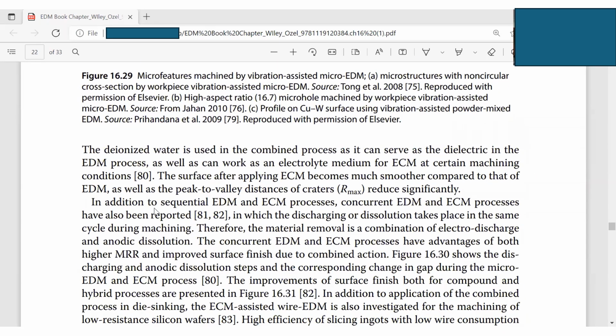water. So in addition to the sequential EDM and ECM process, a simultaneous, concurrent EDM and ECM process has also been reported, in which there is discharging and dissolution. Discharging is from EDM, and dissolution is from ECM, because of the chemical reaction of electrical discharge and anodic dissolution. The concurrent EDM and ECM processes have the advantage of both higher MRR and improved surface finish due to the combined action.